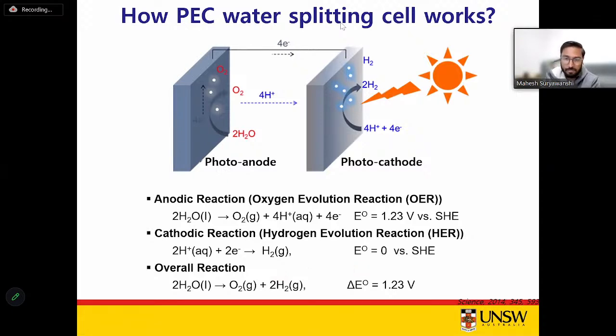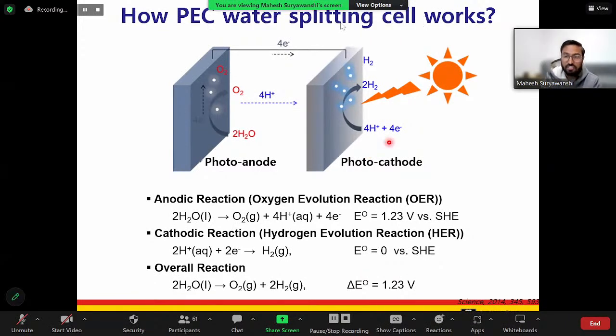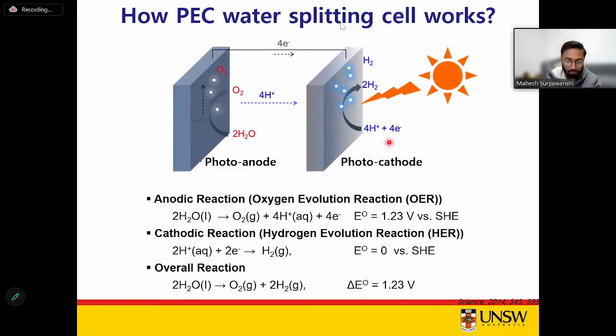So simply, how does this PEC cell work? When the semiconductor, either photoanode or photocathode, absorbs the sun's energy, electrons and holes are generated. It's the same way a solar cell works. The only difference is how these electron and hole pairs contribute to the oxygen evolution reaction and the hydrogen evolution reaction. These photogenerated carriers can drive the reduction and oxidation reactions if the charge injection into the reactants is thermodynamically favorable.